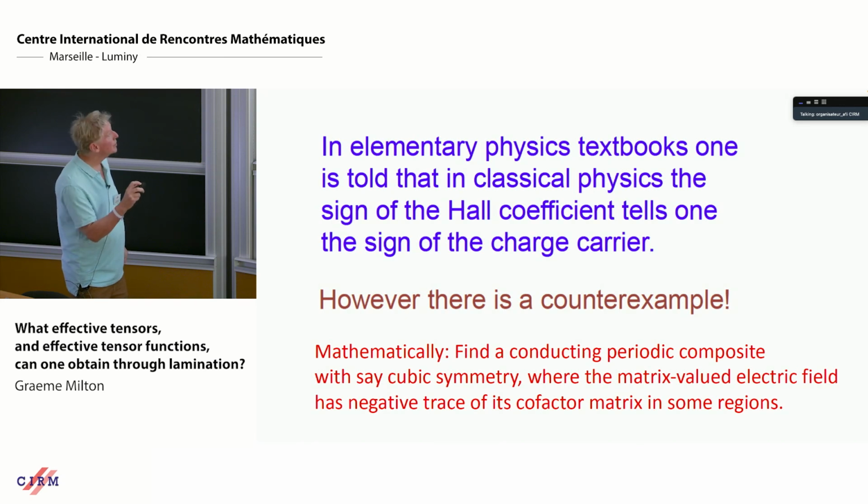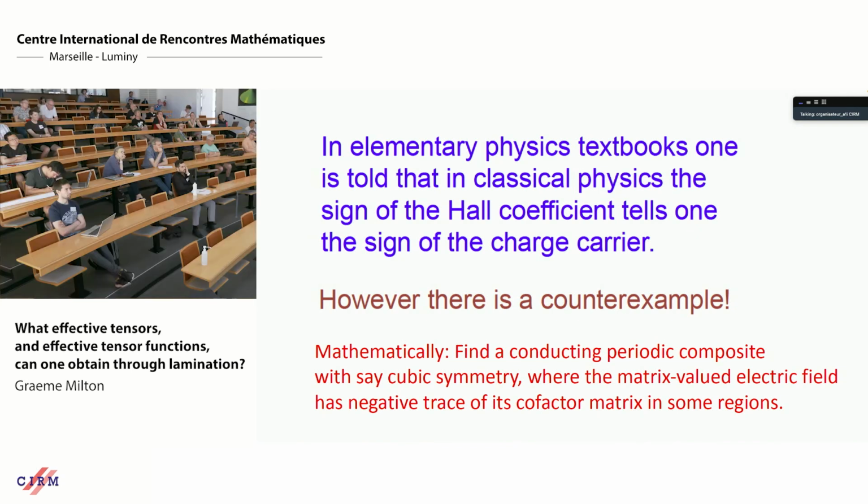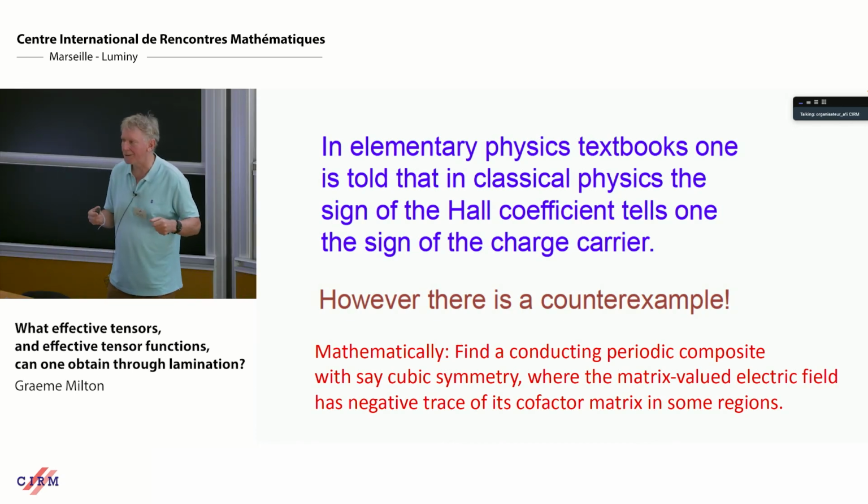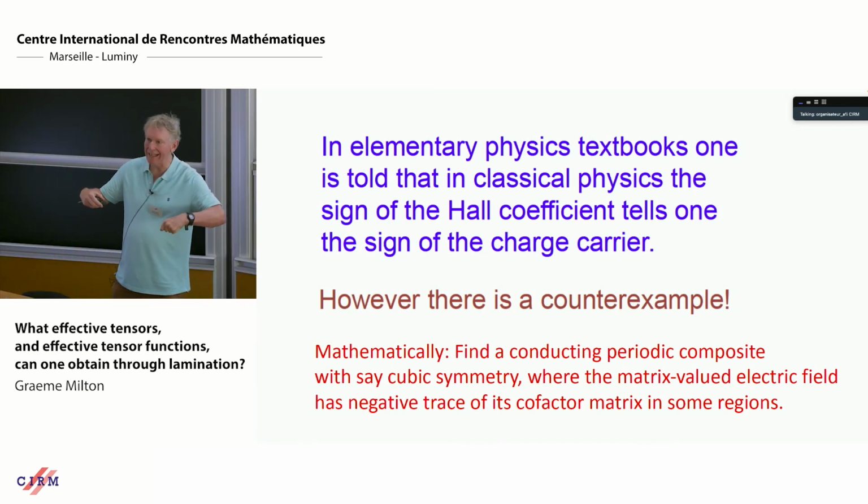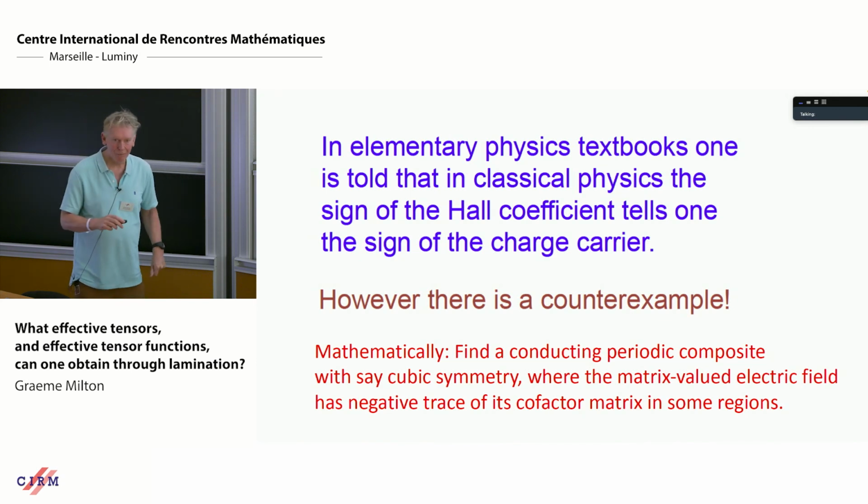Based on that, in physics textbooks, they say that the sign of the Hall coefficient tells one the sign of the charge carrier. But actually, there's a counterexample. That's what we found. You mix materials with a positive Hall coefficient, and you get something with a negative Hall coefficient.